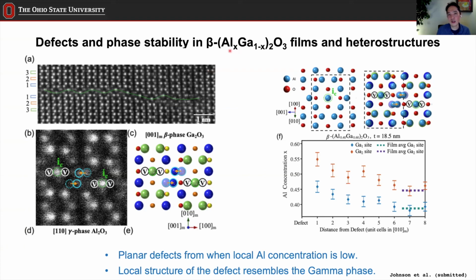This is very important, because if aluminum concentration is high, then this can be the end of the growth. So what's grown below this defect can be the critical thickness. So in fact, the formation of the defect can limit the critical thickness of the film. Okay. So what we provide here is the experimental evidence that the local aluminum concentration, or fluctuation of aluminum concentration over time during the growth, is closely related to the formation of this planar defect as well as the critical thickness of the beta phase film. Okay, yeah, so that's the answer that we were able to provide here to help develop the growth mechanism.